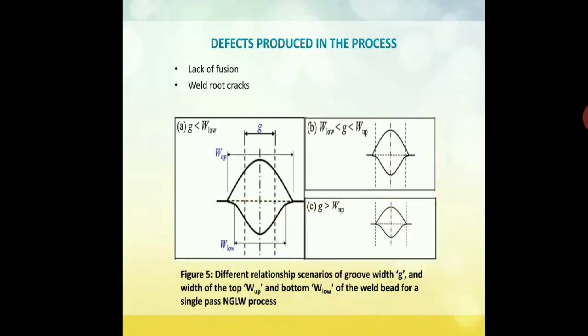The other part of the presentation is NGLW process defects. One of the major issues with this is lack of fusion, which occurs between the side walls of the groove and weldment. And the other one is weld root cracks, which arise due to incorrect selection of process parameters. To obtain a defect-free weld, the width of the lower section of the weld bead should be lower than the groove width, or else incomplete interlayer fusion takes place.